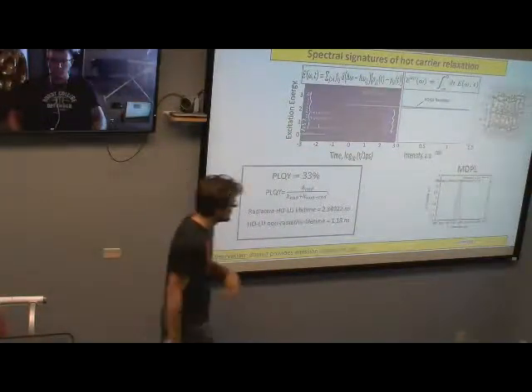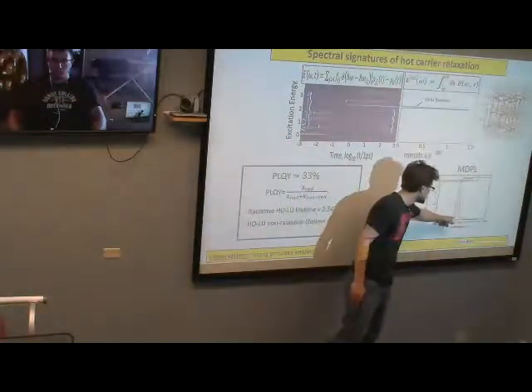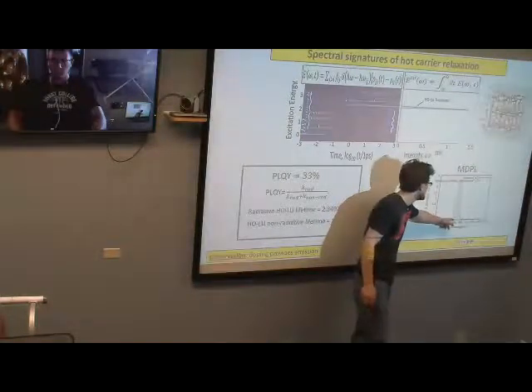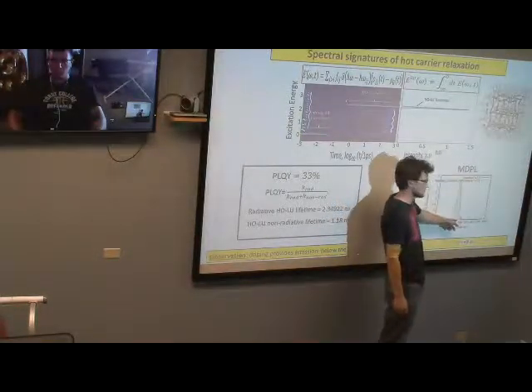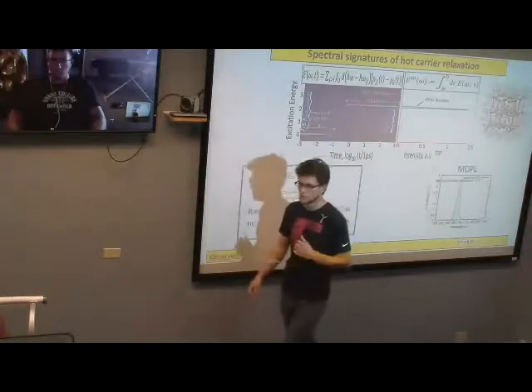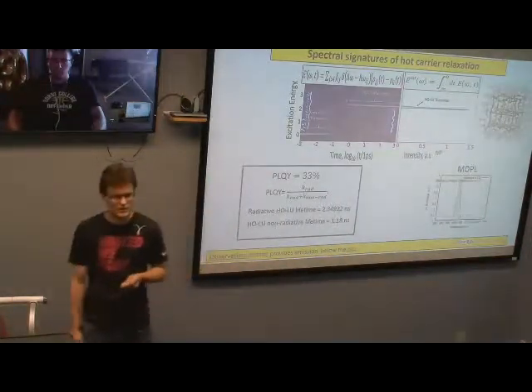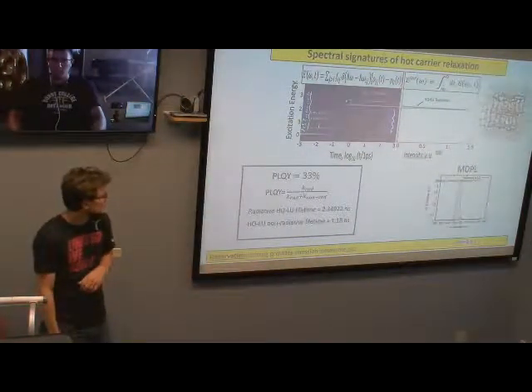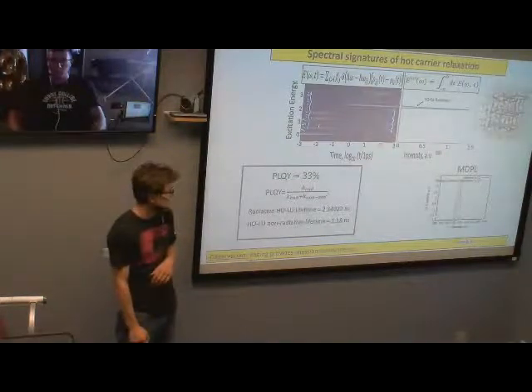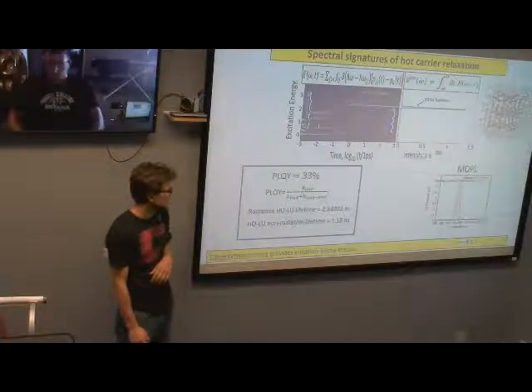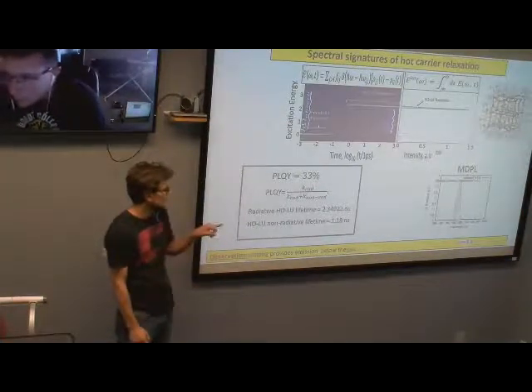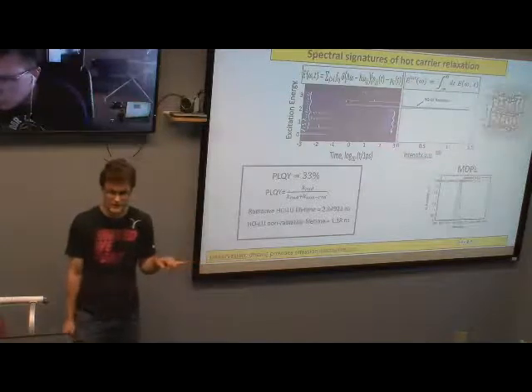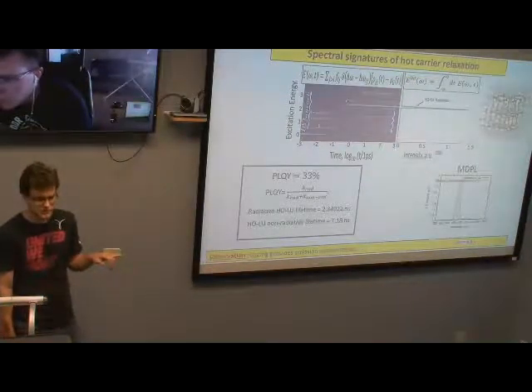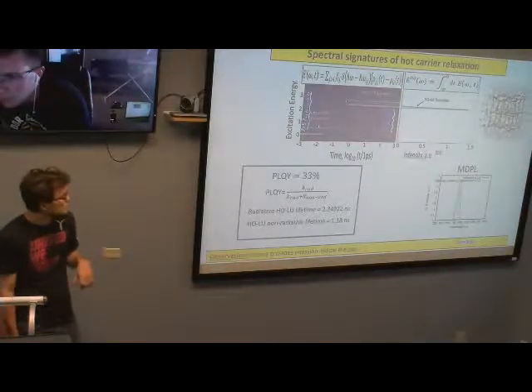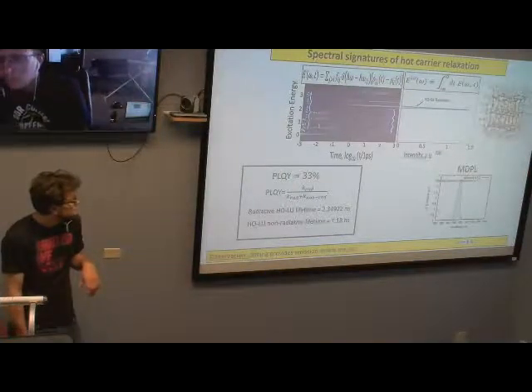So at the tails, you have a lower probability of emitting a photon, while when you're at equilibrium distance, you have a higher probability. So it's a way to try to get line widths of PL in these systems. The green curve is experimental, I think, pulled up from measurements I did in the Hobbie group. And then the red line is what we computed from our molecular dynamics trajectory at room temperature. So, really a good agreement. Yeah, they're in pretty good agreement.